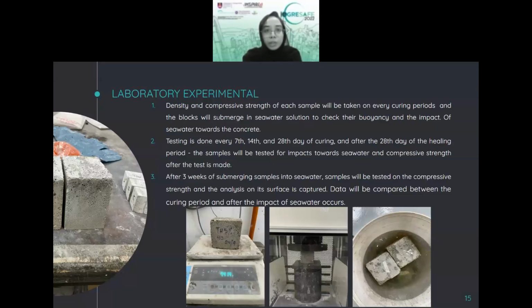So moving on to the laboratory experimental. For this research paper, as I mentioned earlier, I will take the density and the compressive strength of each sample. After 3 weeks of submerging the sample into seawater, the sample will be tested also to check on the compressive strength. And the analysis of the surface of the concrete is then captured so that I can see if there is any cracking or any white deposits coming from the deterioration effect from the seawater towards the foam concrete itself. So data is then compared afterwards.